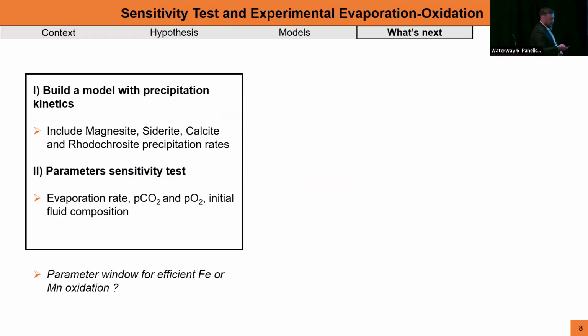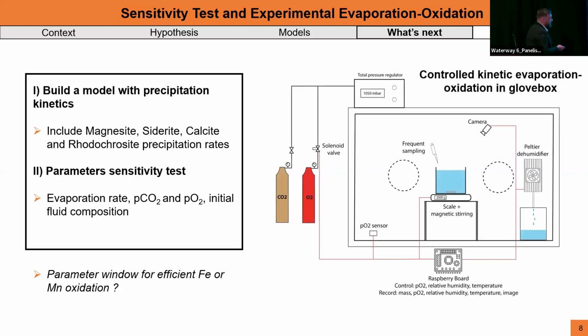And so the next step we're exploring, and actually this model is already done, it's just that I did not have time to put it in the presentation. But when you plug in all the kinetics of carbonate precipitation, as you evaporate, you're going to observe this pH rising and an increased oxidation of manganese and iron. And so instead of having siderite and rhodochrosite, you're going to form manganese oxide and iron oxides. And we're building a setup to prove it as well, in addition to models.